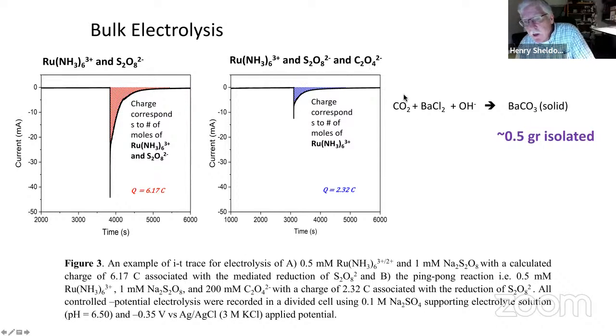Okay, so how do we know this is happening? Jordan takes CO2 and bubbles it through a solution with barium chloride, high pH, to make barium carbonate, which is a solid, and you can isolate this. So an electrolysis experiment like this, she's making macroscopic quantities of CO2, putting in very little current and getting out a huge amount of the product here, all right? Okay, so within error, we measure this charge. We can't measure any extra charge within error due to the reduction of persulfate.